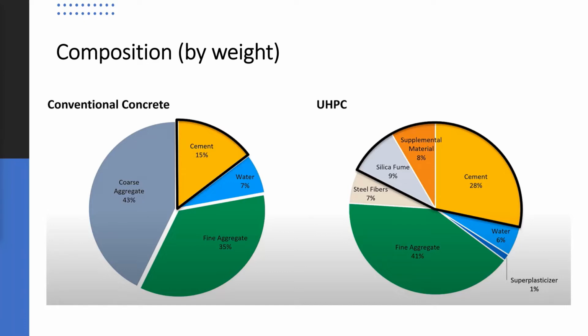UHPC also has a very low water to cement ratio, which is less than about 0.25. And with the careful use of admixtures and accelerated curing, this gives the concrete a very high early strength.